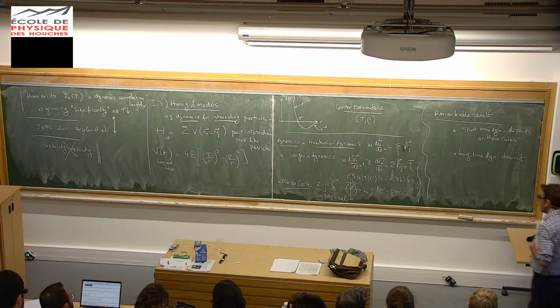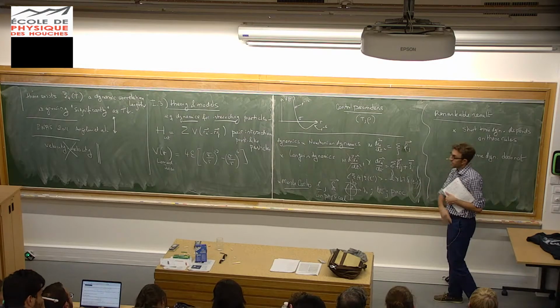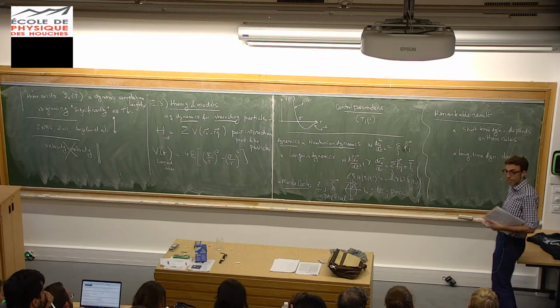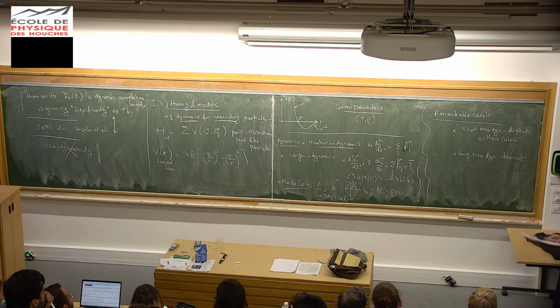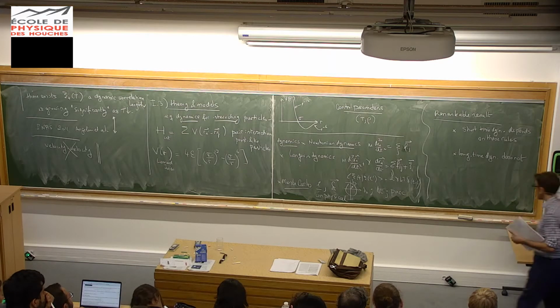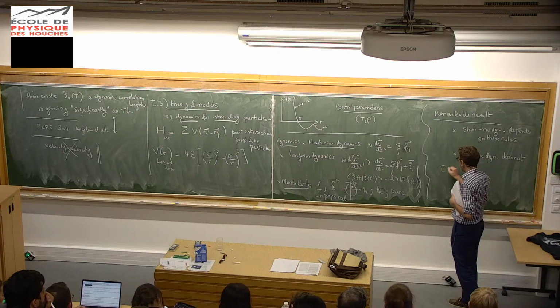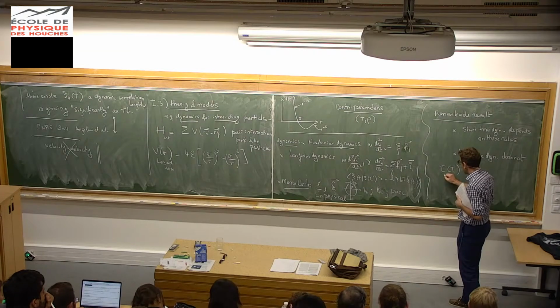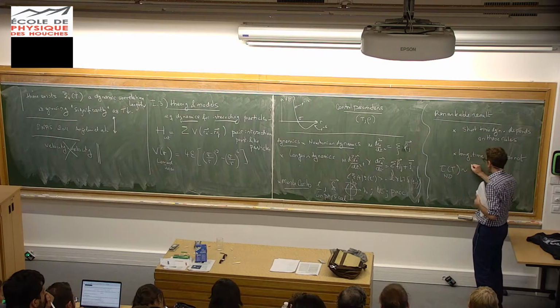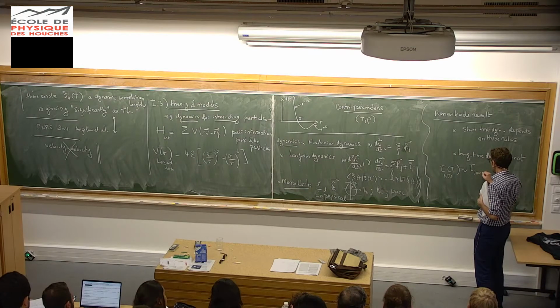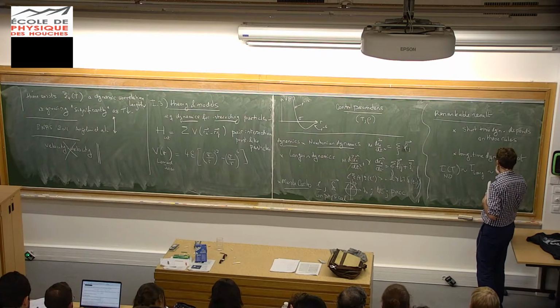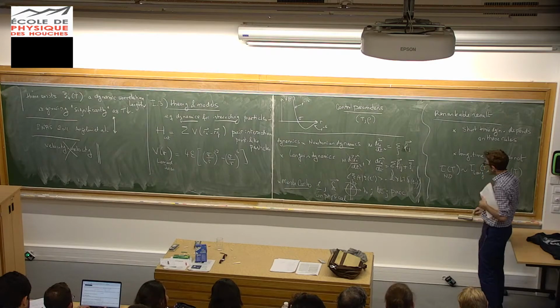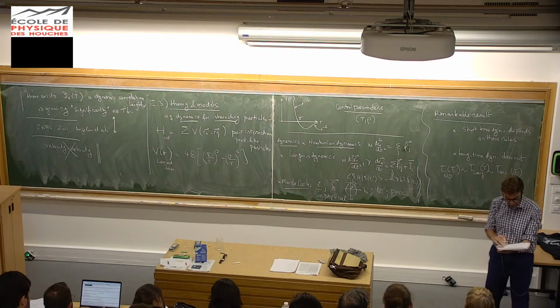And that's a result that you wouldn't have been able to guess, because I told you it's very unphysical. But if you do this and you measure the relaxation time and you plot its temperature dependence, it will be very much the same as the Newtonian dynamics or the Langevin dynamics. So it means that Newtonian, Langevin or even Monte Carlo dynamics, all these things have the very same temperature dependence.